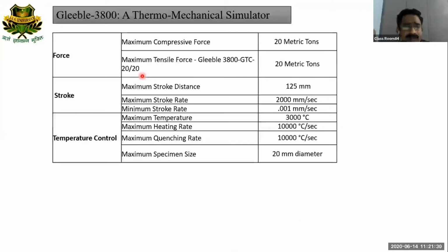With the Gleeble 3800, we first talk about the force. The maximum compressive force it can apply is up to 20 metric tons. The maximum tensile force is also 20 metric tons. The maximum stroke distance is 125 mm. The minimum stroke rate is 10 to the power minus 3 mm per second. It means if you want to compress a sample very slowly, that slow movement is around 10 to the power minus 3 mm per second, so in 1 second it can compress only 10 to the power minus 3 mm. This is the capacity of this particular equipment.